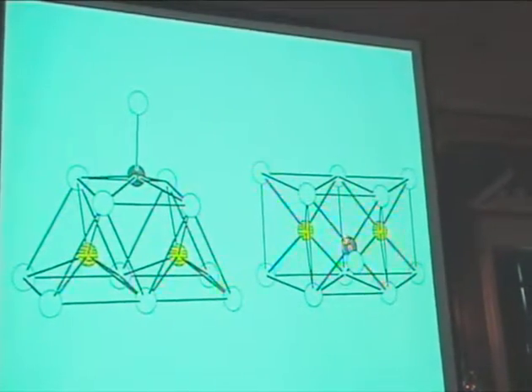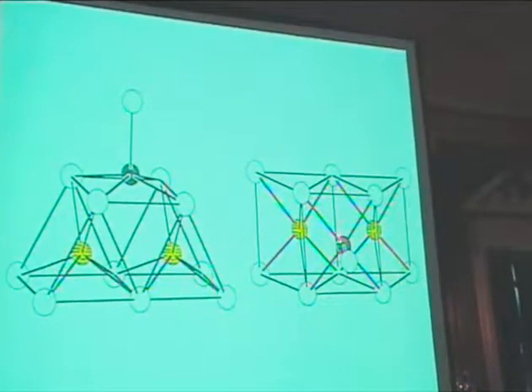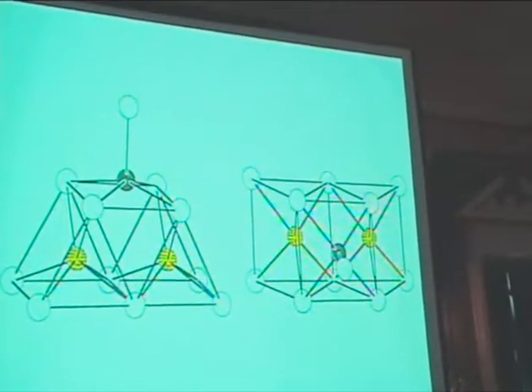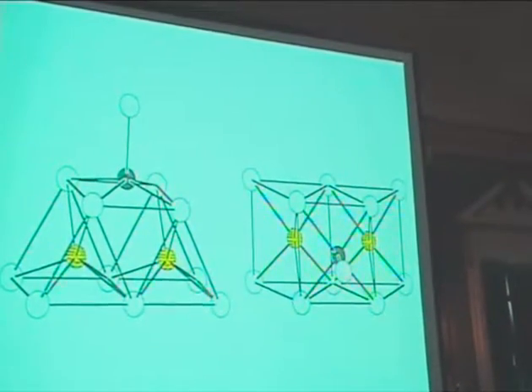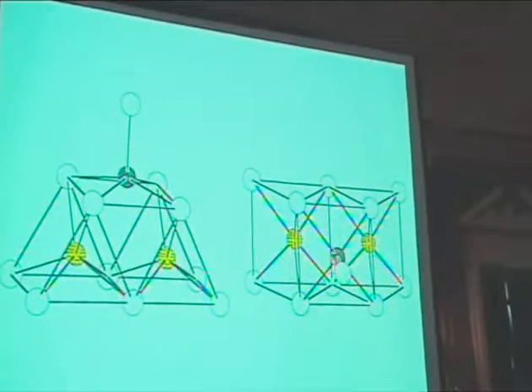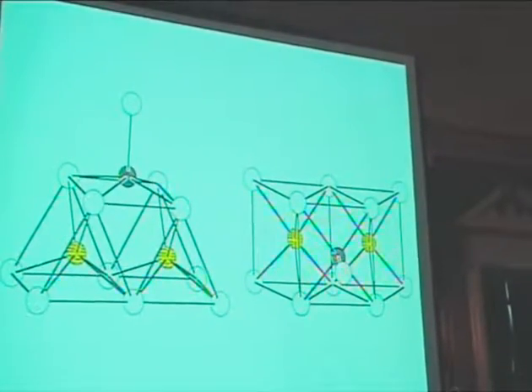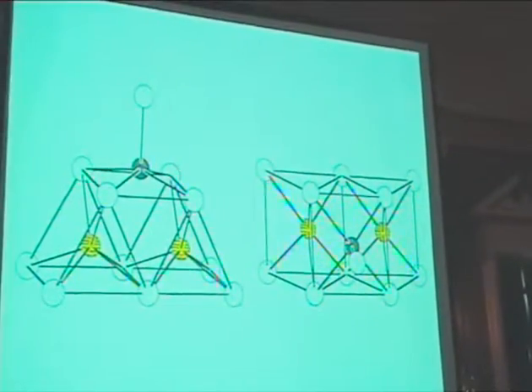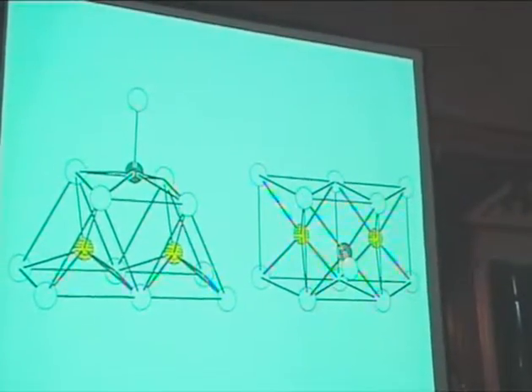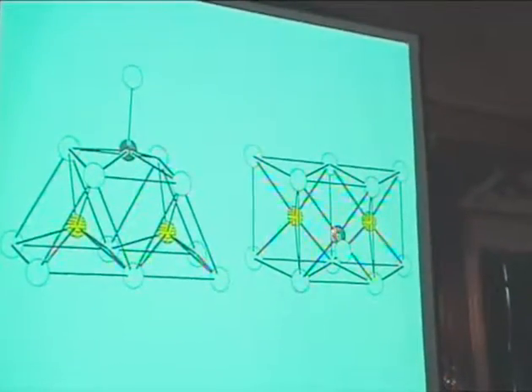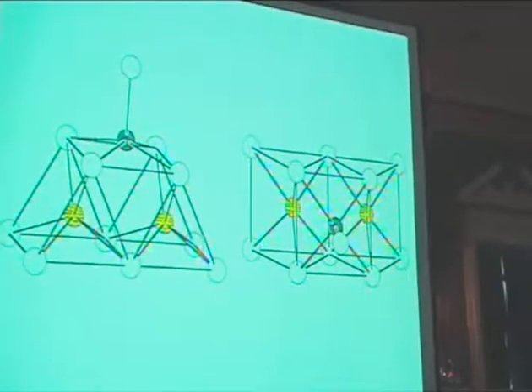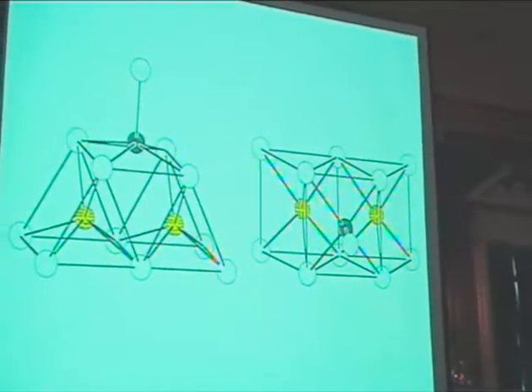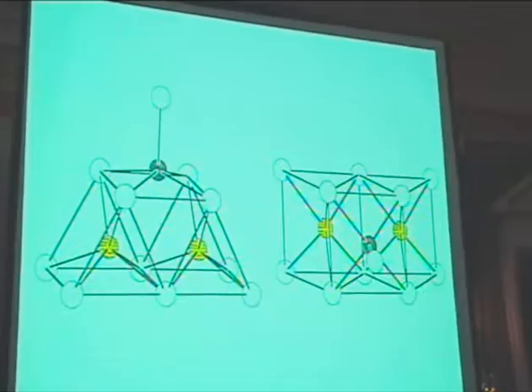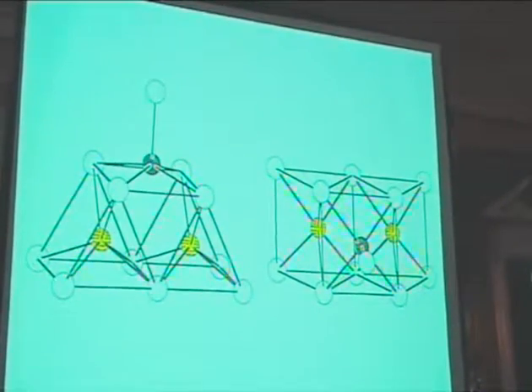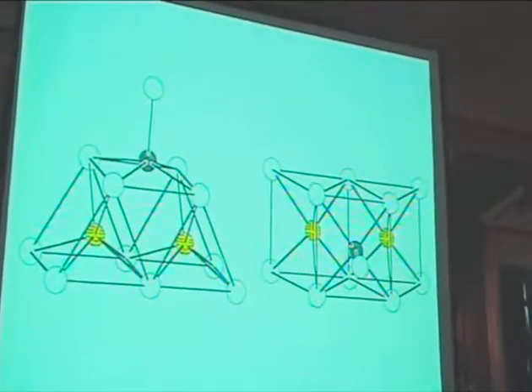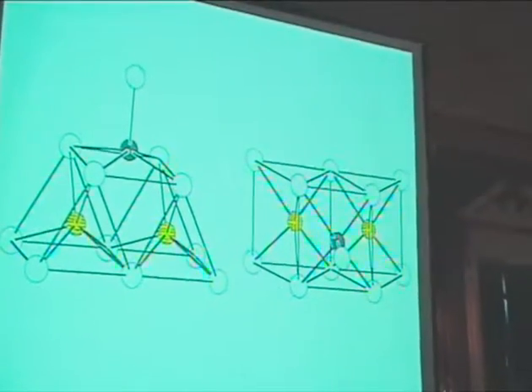Now using the EXAFS, you see there were 3.6 neighbors, which is almost 4. So it looks like it might be sitting on 4. And then there was a second shell, which was 0.7. And so this may be 1 in front of it. And then we saw something like 0.7 of a molybdenum. And that may be the distance from the nickel to that molybdenum. In the ideal structure, there should be 2. So this suggests that there is some disorder. Not all the sites are really seeing the ideal picture which you have here. Or there is a reason that we have lost intensity. I'll come back to that.